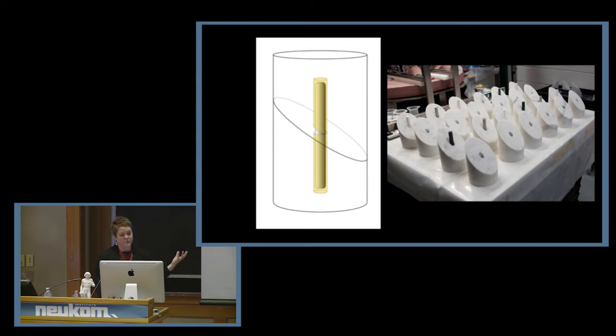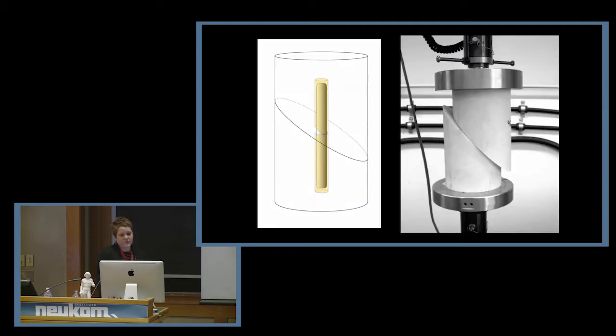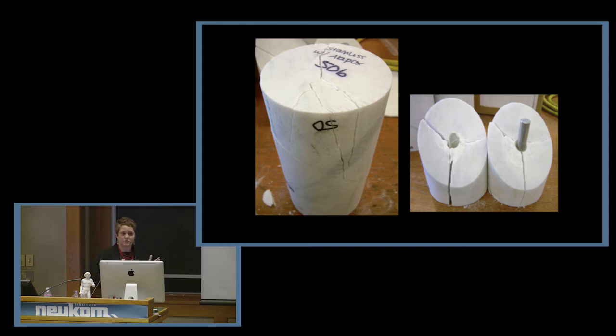With stainless steel and carbon fiber being the stiffest, and polycarbonate, which is kind of like acrylic, like plexiglass, being the least stiff, those were pushed to failure. And the results showed us something that wasn't very surprising, which was that stainless steel, which is significantly stiffer than marble, when pushed to failure, causes the marble to break. Now, this isn't something that would happen naturally in the sculpture. The static forces, just the sculpture standing alone, don't create enough force to break the marble if there were a little stainless steel pin in there.